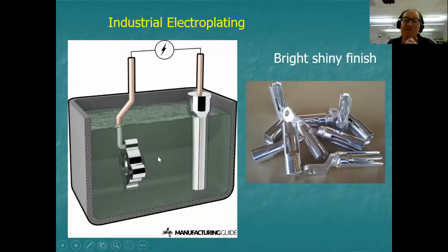And the idea is that as we deposit tin from the solution, we replace it with fresh tin from the electrode. So the counter electrode slowly dissolves and gets smaller, whilst we build up the thin but finite layer onto the object. And if we do it right, we can plate many hundreds, even thousands of objects with just one electrode. So this stays in the bath continuously, and these just go in once, get coated, and then get taken out and replaced by another batch. And this process just goes on and on, many hours a day.